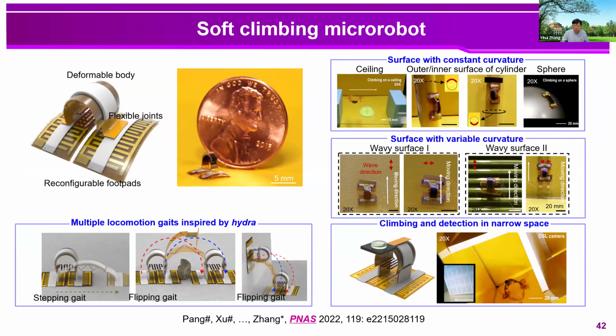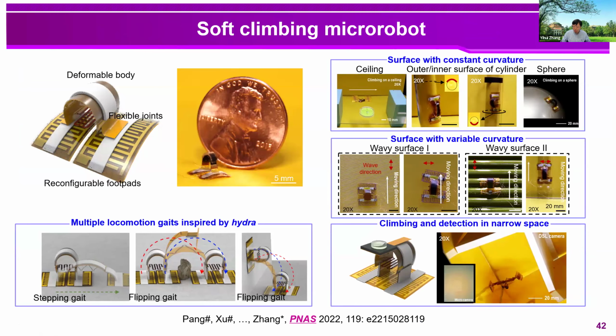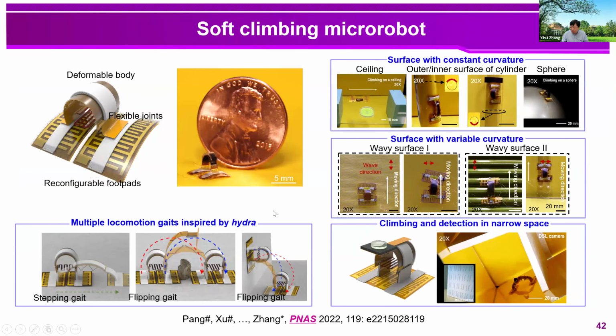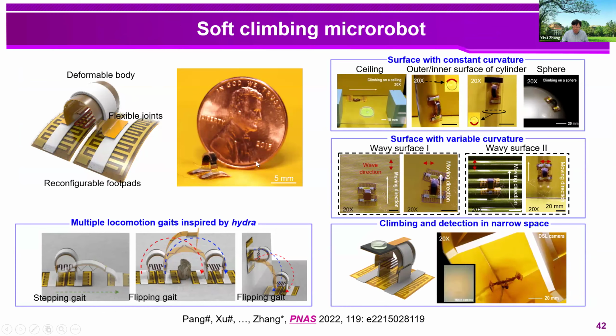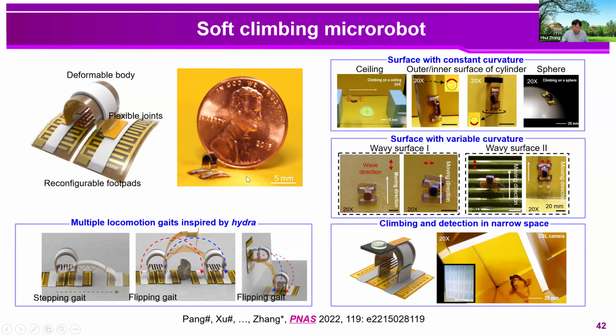And here shows a soft climbing microrobot. This work was inspired by the pioneering work of climbing robot done by Professor Guoying Gu from Shanghai Jiao Tong University. In this example, we use the 3D assembly approach to design a set of LCE-based 3D microactuators with large actuation deformations. Based on these microactuators, we can fabricate a class of 3D microrobots, which is much smaller than a coin. And due to the conformal footpaths, the microrobots can climb on various different curved surfaces with both constant curvatures and also varying curvatures.